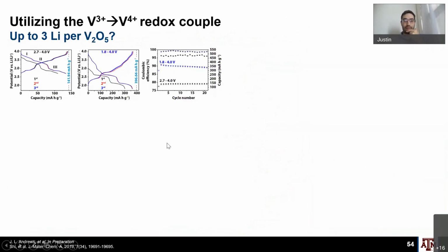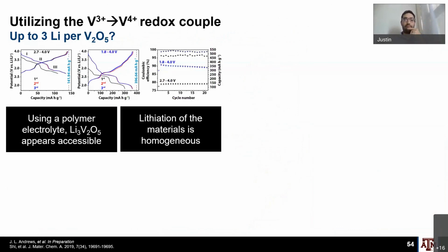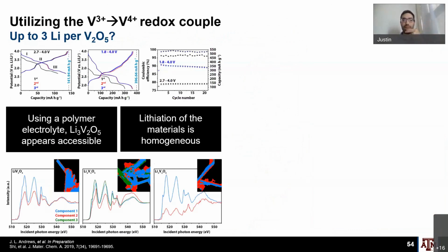What's really cool about this is that it not only confirms a lot of our nudged elastic band calculations in terms of where the lithium goes and how it diffuses, but we've now been able to get up to 3 lithium into zeta V2O5 without significant phase rearrangement, because it's a one-dimensional tunnel structure, whereas as I mentioned before, in alpha V2O5, these phase transformations prevent us from getting beyond 1 lithium per V2O5. And through STXM, we've been able to show that the phase homogeneity in these materials, because it's a one-dimensional tunnel structure, is much greater than in alpha V2O5, where we get these core-shell patterns. In zeta V2O5, we're not able to detect significant inhomogeneity in the way that these lithiate.